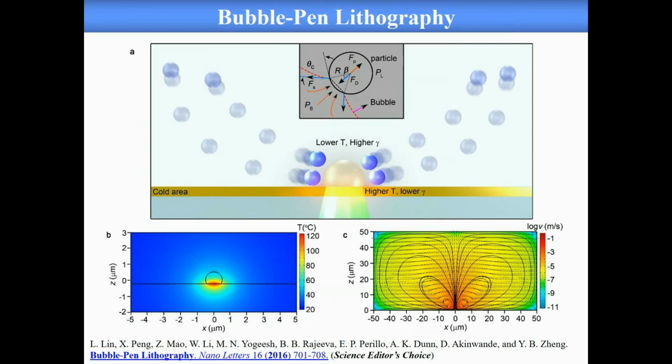So in this case, once you have the laser power, I say it's high power, it's actually not that high. Compared with optical tweezers, it's still low power. The reason we can use low power to generate a bubble here is because of that thin layer. This thin layer is golden nanoparticles, small golden nanoparticles, which we know support surface plasmons. In the first few slides I mentioned, once you have surface plasmons generated, you can concentrate the light at such a small scale that you have very high conversion efficiency of light to thermal energy.